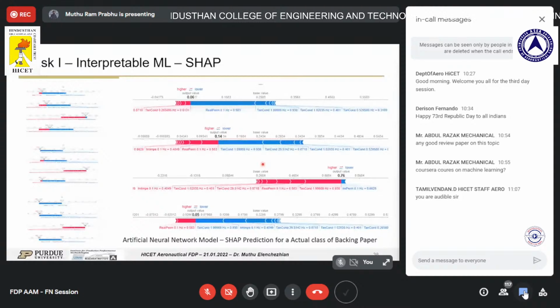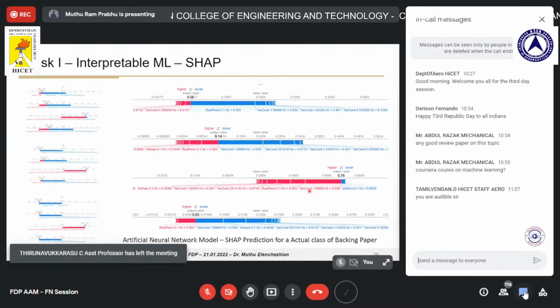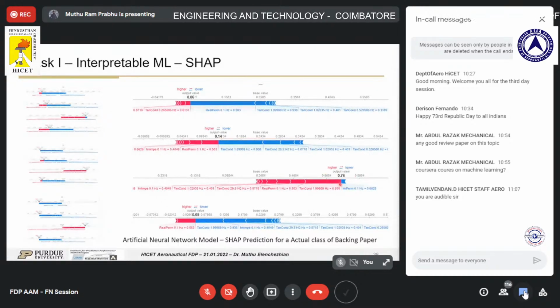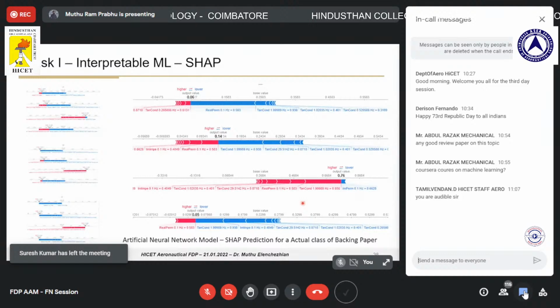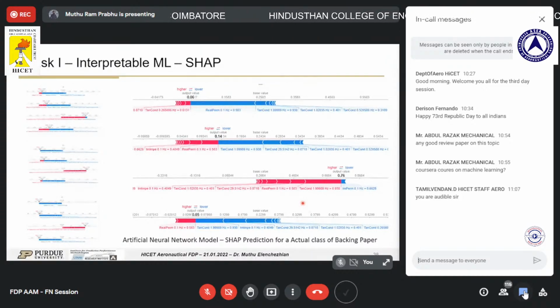So let's say the model predicted that your defect is going to be the third class over here, which is the backing paper class. Then you can say for this backing paper class, which has the highest value over here, as in all the other three models as well, which particular values contributed to them most. Here you can see it's the real permittivity at 0.1 hertz and the conductivity value at 2 hertz. And one thing you noticed is that different models give different results, so it's more important to validate it in a further state.